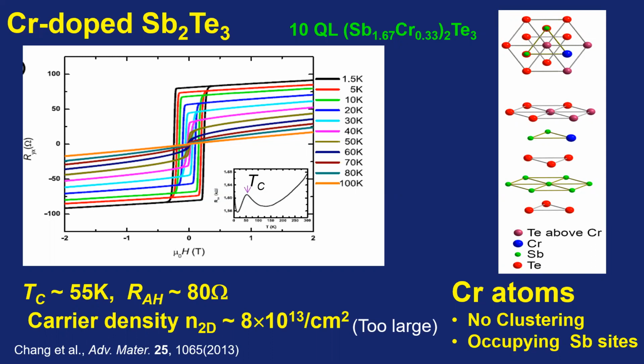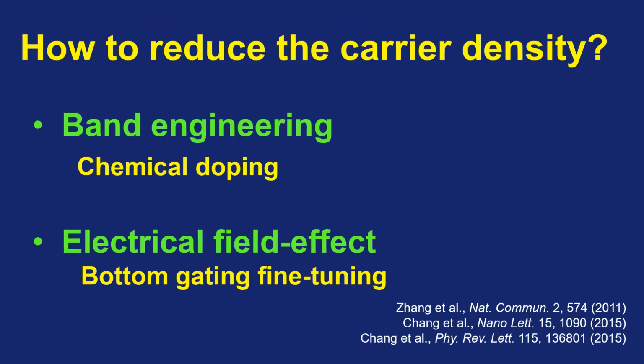So until now we have achieved the thin film of topological insulator. We also demonstrated the ferromagnetic state in this kind of magnetic doped topological insulator. The third step is how to reduce the resistivity, how to tune the chemical potential into the magnetic exchange gap. We use two methods, chemical doping and the gating effect. Let's check the first way.